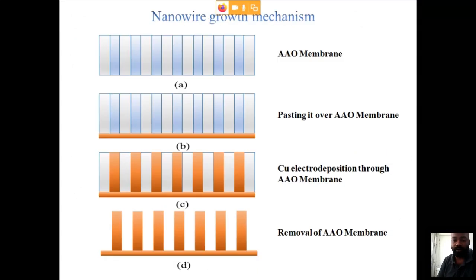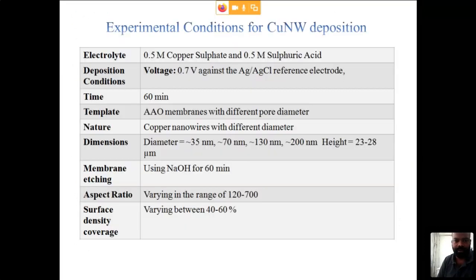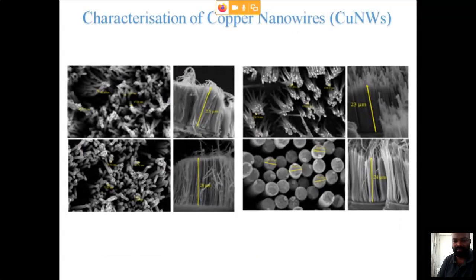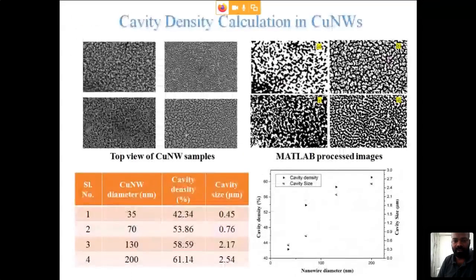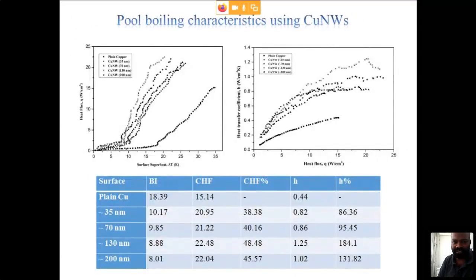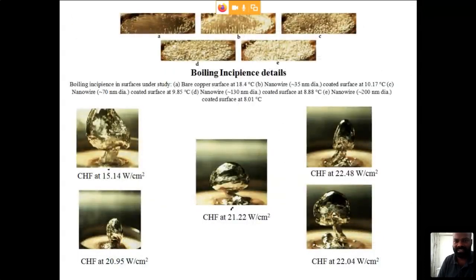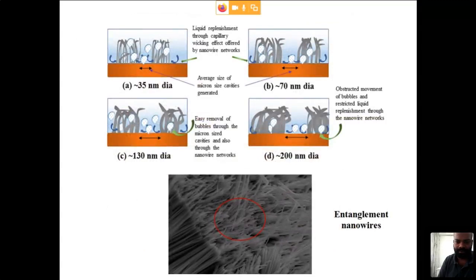Initially we used metal copper nanowire. This is the mechanism of growth, experimental conditions. These are with different diameters. You can see we have grown copper nanowire using different diameter values, and we have measured the pool boiling performance, and we have seen that as the diameter increases, the performance increases, both in terms of CHF as well as heat transfer coefficient. This is a basic bubble dynamic mechanism, what happens because of this nanowire coating.